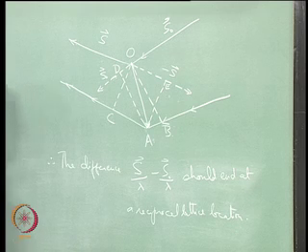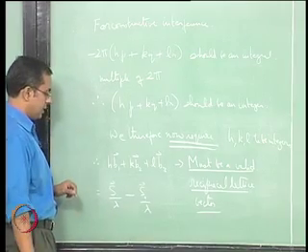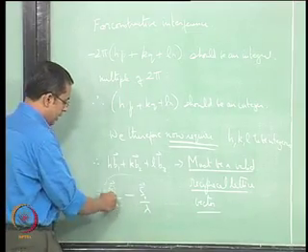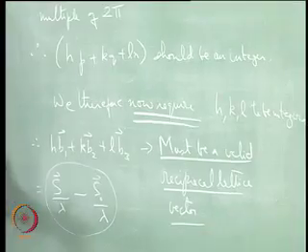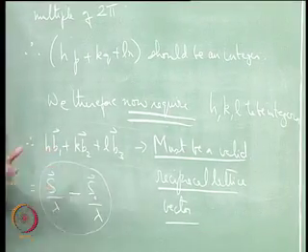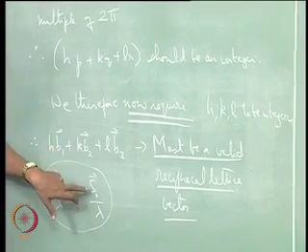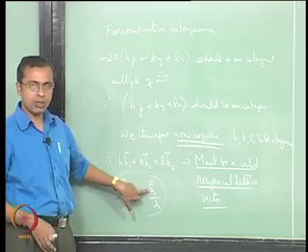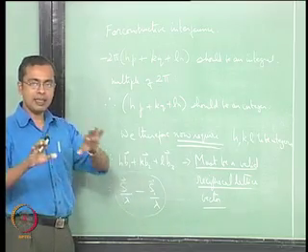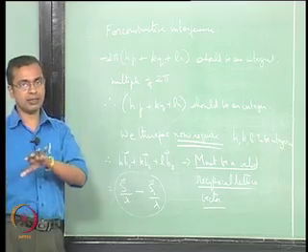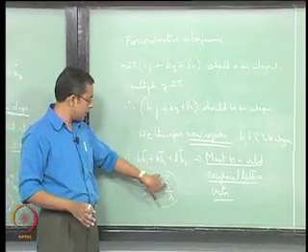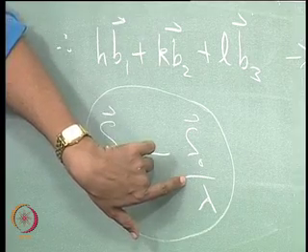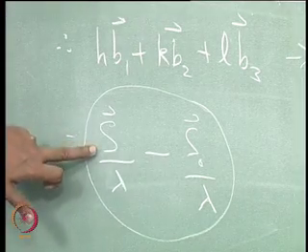If you look at our equation here, we have two different quantities. We have a quantity on this side of the equation which basically gives us all the properties of the waves arriving at or leaving the lattice. This is the direction in which the incident wave is arriving, s naught, and 1 by lambda is the magnitude of the wavelength in reciprocal quantities. So that gives us the properties of the incident beam. This is the properties of the diffracted beam.